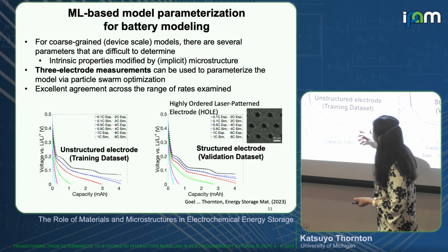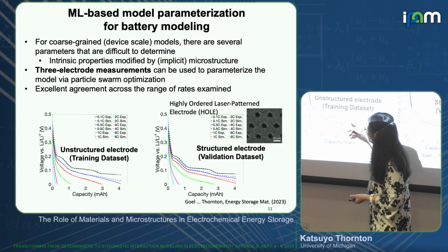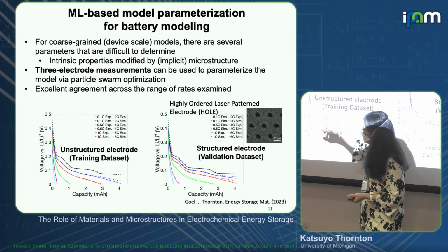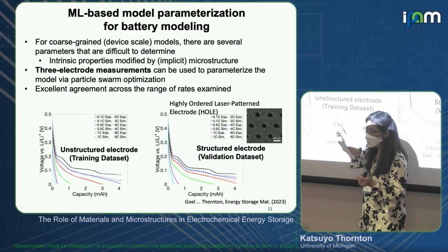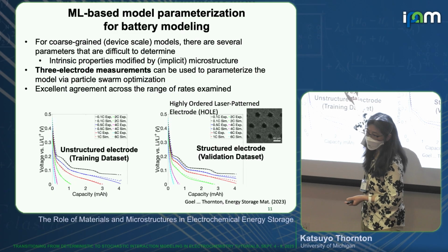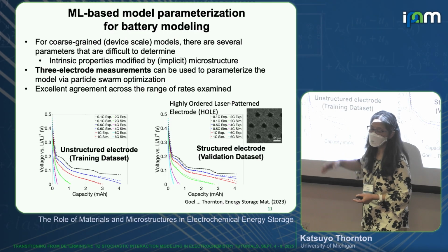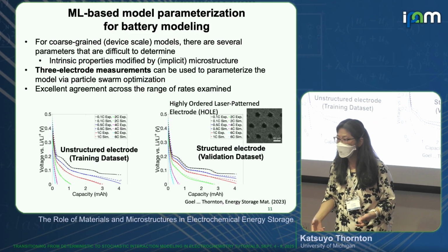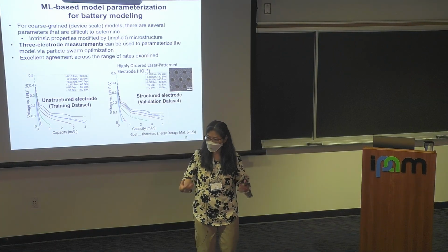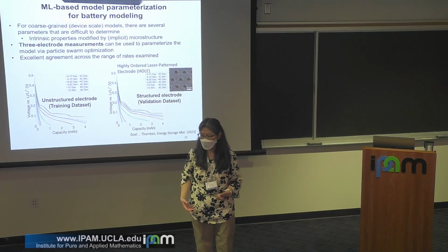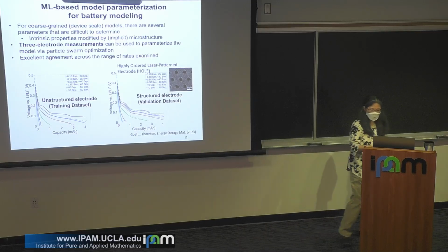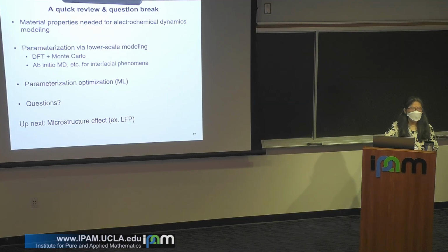So there's a systematic way that you can get this right. You can constrain the thermodynamics with the lower rate. And then you're left with some kinetics parameters, which makes it a bit easier to converge because there are fewer parameters by that time. Does that answer your question? Okay, great. Any other questions?